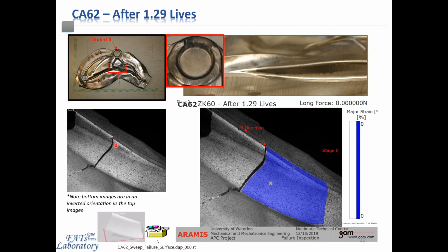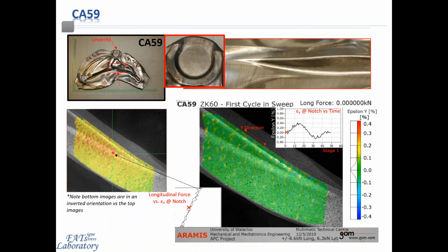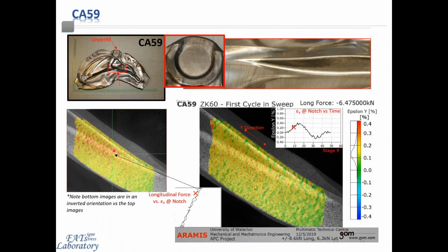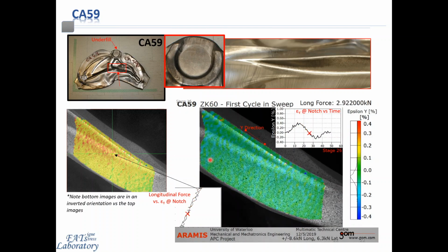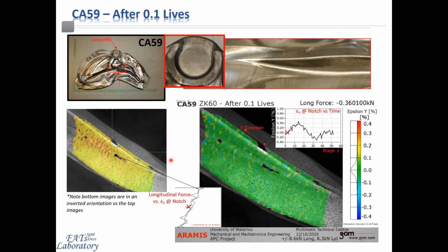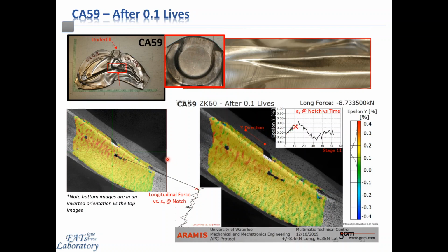Now, this is kind of just a brief summary of the nature of the fatigue failure for one of these particular components. But as I had mentioned previously, due to the variations in the forging process and the resulting defects that manifest themselves from those variations, we can look at the other components to get a sense of the variability in the types of failures that we would observe. Now looking at another component in the first cycle, it's largely identical with no indicative signatures of any incipient defects. Moving to 10% of the fatigue life, and still nothing has really changed from the previous component.